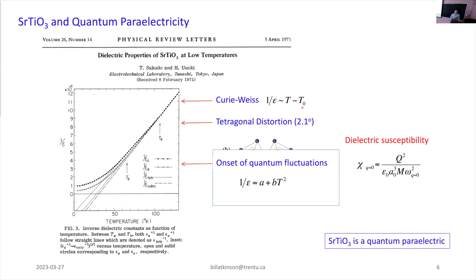But the bigger thing that you notice is that when you get to low temperatures, below about 50 Kelvin, there's this deviation where the dielectric function stops being Curie-Weiss-like. And in fact, it saturates. So instead of crossing through zero, signaling a divergent dielectric susceptibility, which would tell you you have a transition, it just saturates at a finite value.